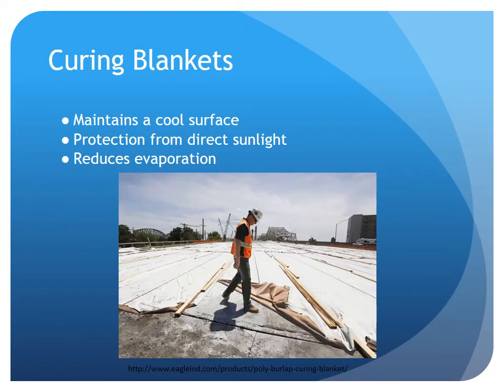Curing blankets are commonly used where there are very hot outside temperatures. They maintain a cool surface by providing a barrier from direct sunlight. Curing blankets are water resistant and decrease evaporation by keeping the concrete at a higher humidity level. The resulting increased hydration will lead to a greater strength development in the concrete.